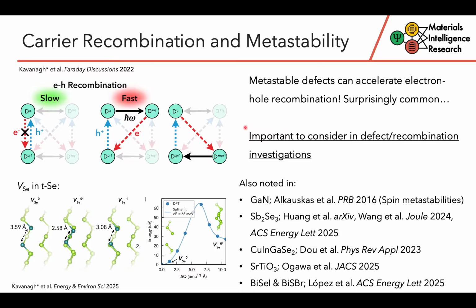So when defects capture electrons or holes non-radiatively, so through phonon emission or absorption, the presence of metastable defects can actually act to really catalyze these processes, because they essentially open up alternative pathways for these cycles to occur. So instead of just capturing between two possible defect structures, you now can have these intermediate metastable states, which really